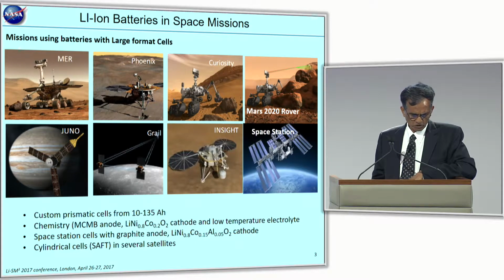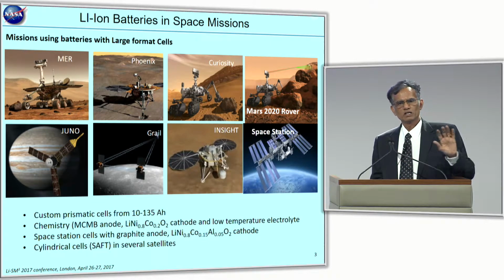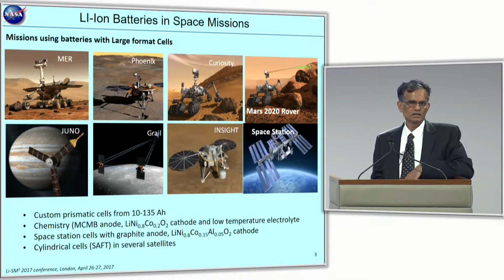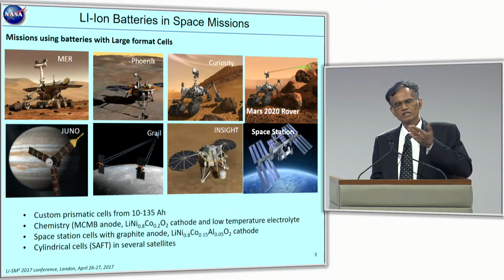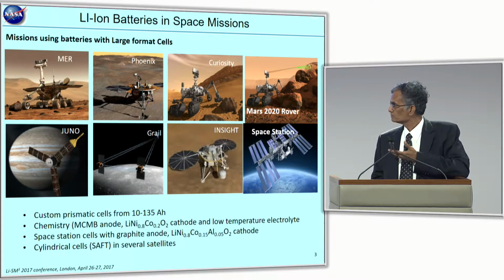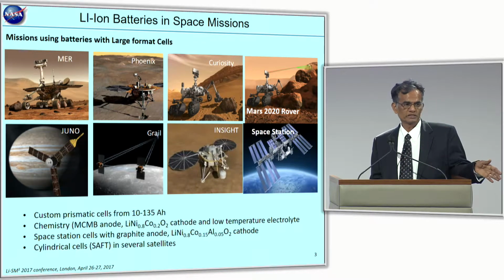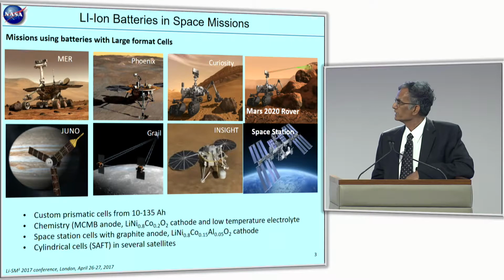These are all Mars type missions that we have, except the last one, which is the space station. Here our approach was to use batteries made by an aerospace manufacturer within the US, and these are custom made cells. The cells range from anywhere from 10 amp hours to 50 amp hours, depending on the mission need. And these are made, as I said, with some specific chemistry in place. In fact, we used nickel cobalt oxide chemistry with MCMB here. But the interesting thing is here we were able to utilize some of the electrolytes that were developed at JPL that are designed for the low temperature operations down to -20, -30 degrees C.